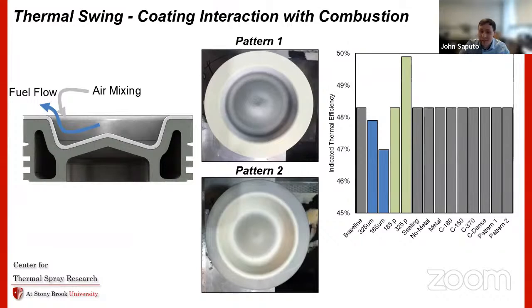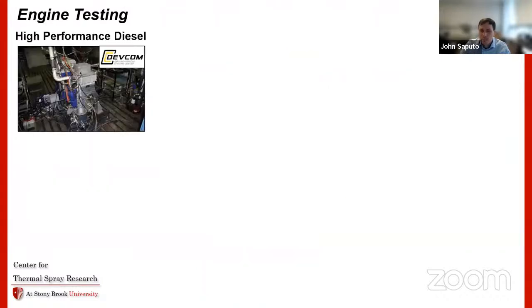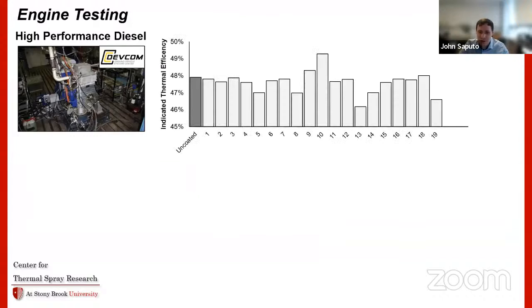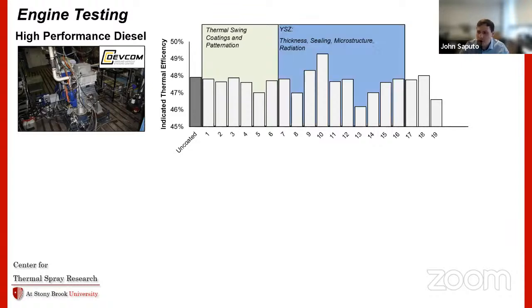So it's beginning to be a bit of a repetitive story here: you don't see a whole lot of change in efficiency in these systems, basically no matter what you do. This is the sort of high performance diesel testing that I was talking about before. We did this to death. About 20 engine tests performed using thermal swing coatings, patternation, zirconia coatings, changing the thicknesses, using different sealings, different microstructures, radiation coatings. There's a lot that I didn't even talk about in here. We tested coatings up to the millimeter scale in thickness. Didn't really see any changes from any of this. We did things with low conductivity metals, and some instrumentation testing that I'll talk about a little bit later. And then we went back and did a bunch of uncoated engine tests.